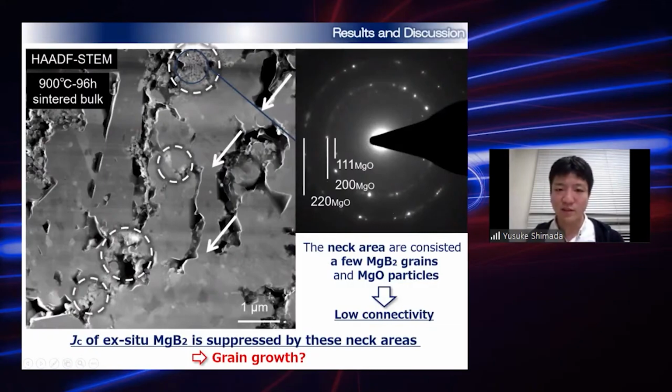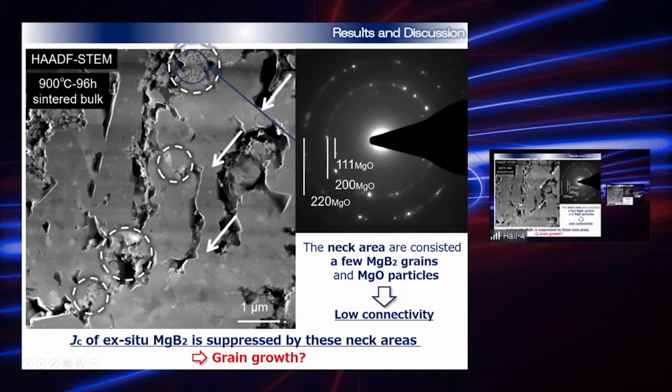I would expect that mainly you have MgB2, and if you have a sintering process or any process with mass transport, then if there is a reaction that forms this MgO somewhere, I would expect it to accumulate in interface areas, so that in a polycrystalline material it would be in the intergranular region, in granular junctions in some way. Or is that not what you observe?